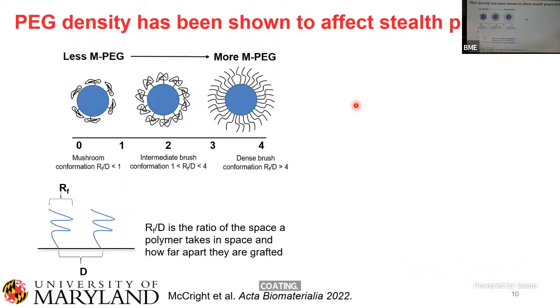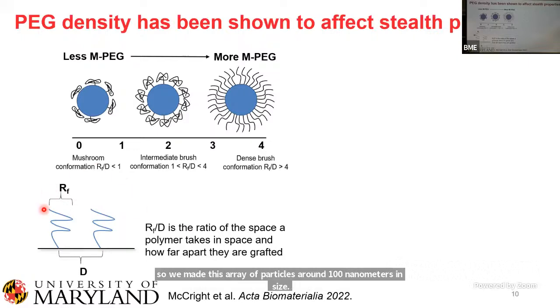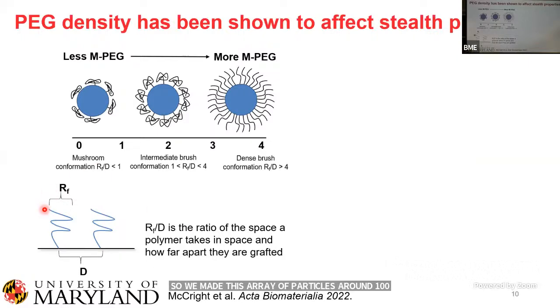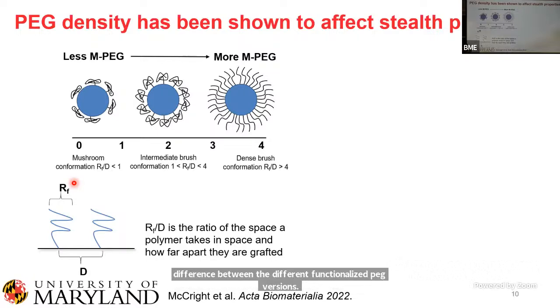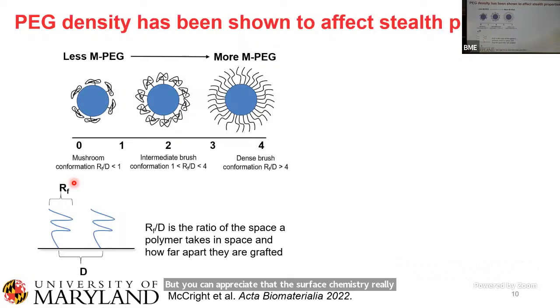And so essentially, this is a little bit of material science for you guys. Essentially, the way to measure this is the RF over D. So RF is the Flory radius. So this is basically the space that the polymer would naturally take in solution without any constraints. And you divide it by D, which is the grafting distance between each of the polymers. And so that allows you to get an estimate for what the conformation of PEG is on the particle surface. And so generally, when you're talking about somewhere in the range of 0 to 1, 1.5, you're talking about this low density mushroom conformation.